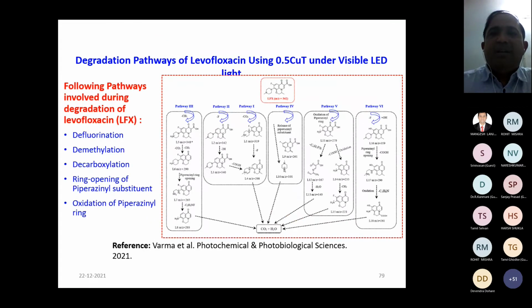So in this paper we tried to identify pathways of levofloxacin degradation, and through LC-MS spectra we found that the levofloxacin degradation is carried out by 4 to 5, 6 ways: through defluorination, demethylation, decarboxylation, ring opening of the piperazine substituent, and oxidation of it. We carried out this LC-MS analysis and reported it in the open literature, and finally it is converted into CO2 and H2O, that is the hypothesis.